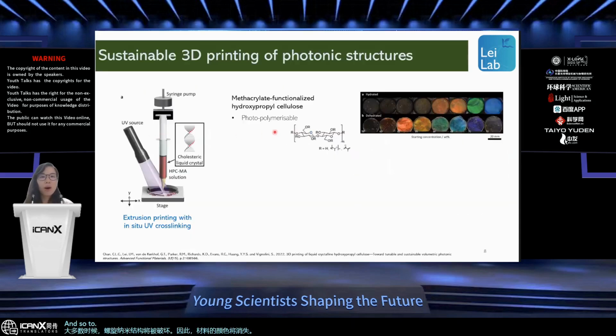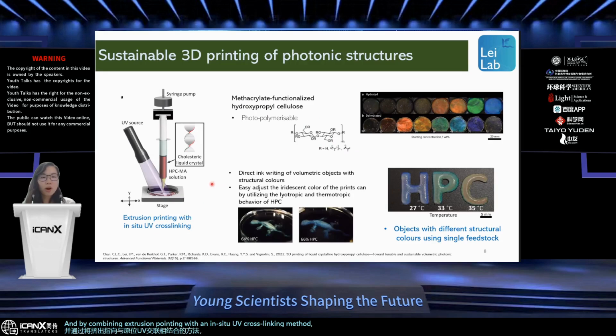To address this problem, we developed a methacrylate-functionalized hydroxypropyl cellulose material. This material is photopolymerizable. By combining extrusion printing with an in situ UV cross-linking method, we are able to do direct ink writing of volumetric objects with structural color. With the in situ UV cross-linking method, the materials can be quickly solidified, and the helicoidal nanoarchitectures can be locked in by the UV cross-linking mechanism after we extrude the materials out.